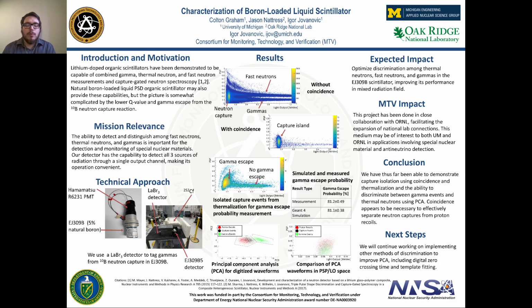However, due to the lower Q value of the boron capture reaction, as well as energy deposition from the de-excitation photon from lithium-7, the traditional pulse-shape discrimination that's used to isolate capture events is not effective here. So we've been demonstrating alternate methods of isolating capture events.